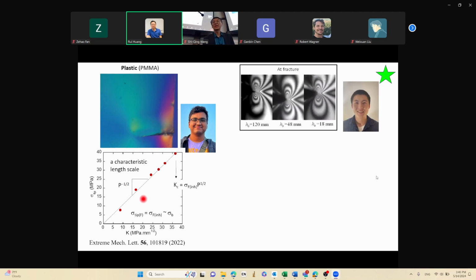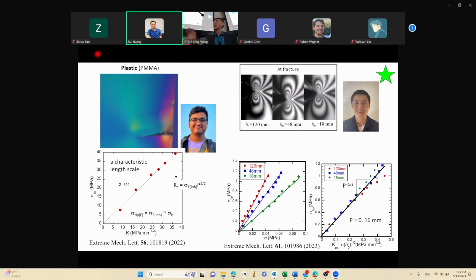So here's the stress you find. No matter what your height is, the fracture occurs at the same tip stress level. And you can look at this for different H's, and you can collapse into a master curve when you use this loading parameter K related to height. Nothing new there. And in any case, we find that there is a different origin of why Rivlin-Thomas works here. That works because the tip stress is reaching the same level, and the tip stress is enhancing more and more as you use higher height of your sample.